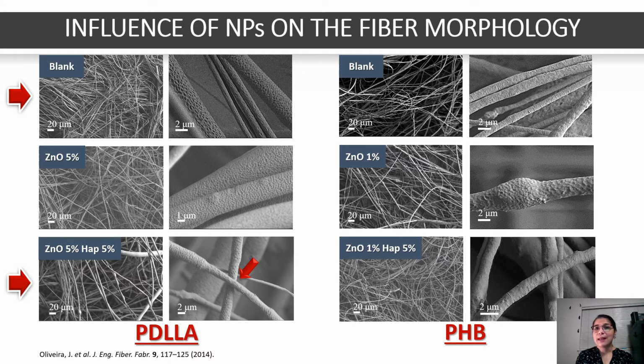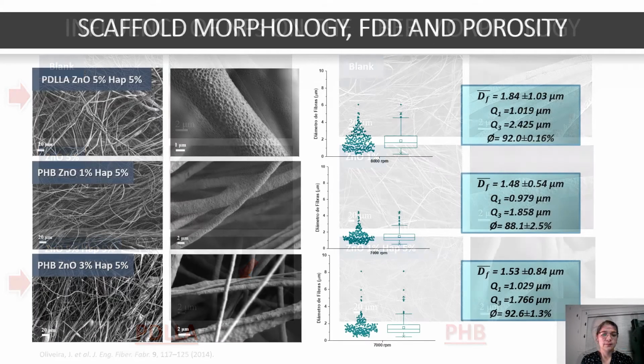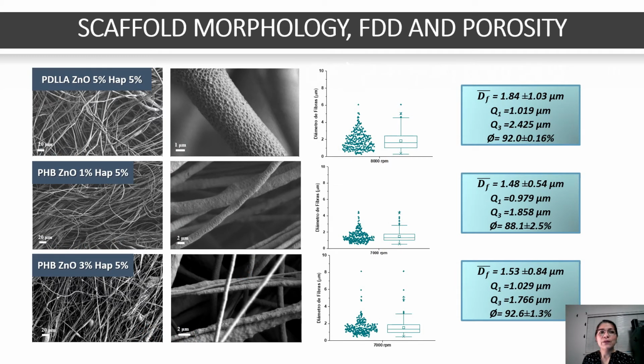Due to that characteristic of the ternary system, it could be inferred that the phenomenon described had an influence on the fiber appearance. About PHB, right images, the incorporation of nanoparticles has a greater impact on the fiber surface appearance compared to PDLLA. Based on the previous optimization phase, as I commented in the experimental methodology, the ideal condition for obtaining the scaffold was selected. In the SEM images, the three selected systems are presented.